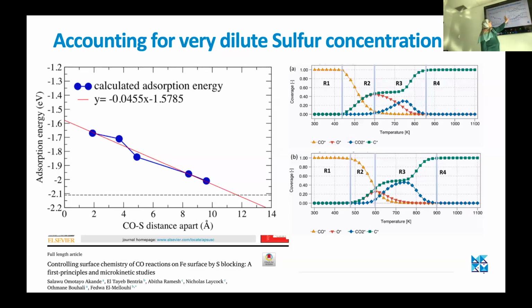So then what you can see is the most important part of this metal dusting. This is the surface coverage, where we are counting what species are on the surface. You see in regime number 1, the surface is covered by CO molecules, and these are not yet dissociated. Then they start to dissociate, and we start to see the emergence of carbon deposition. We also have oxygen, and we have some CO2 that forms at a later stage. So this is the window of the metal dusting here.